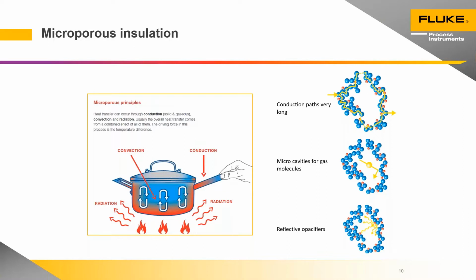The degree to which it's compressed controls the size of the cavities between the spheres. And there's very careful control on the compression to ensure that convection within those cavities is reduced to a minimum. And to reduce any radiative heat transfer within the material itself, the spheres are coated with a reflective opacifier. So that's how the microporous insulation in the thermal barriers is working to reduce as much as possible heat conduction through to the data logger.